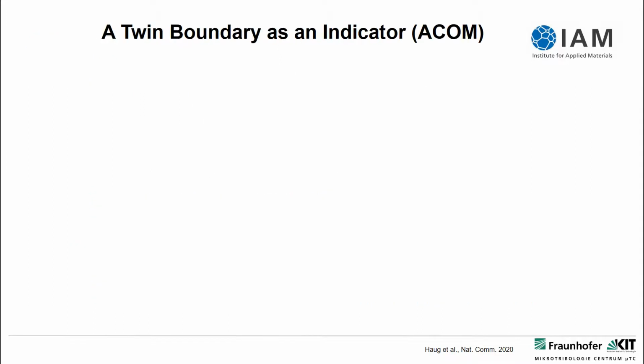What we did here is we looked at this TEM foil using a method called ACOM, automated crystal orientation mapping. That's basically mapping diffraction spots with very high resolution on the TEM foil, and by doing so, getting information about the crystallographic orientation inside the TEM.